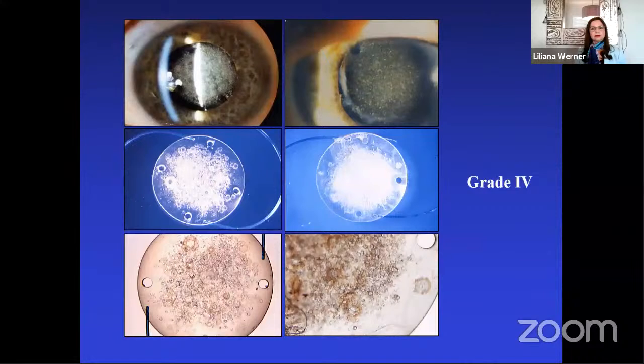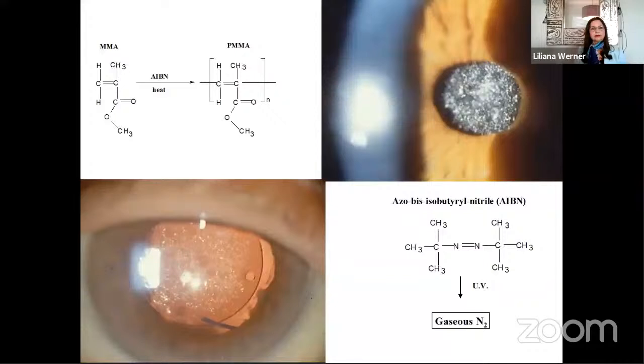These clinical, gross, and light microscopic photographs show IOLs with grade 4 snowflake degeneration. When the lens has this appearance, the case is usually clinically significant, requiring explantation. The most accepted hypothesis to explain the condition is that the lenses were manufactured with an excess of a molecule that's used to initiate polymerization for the formation of PMMA.